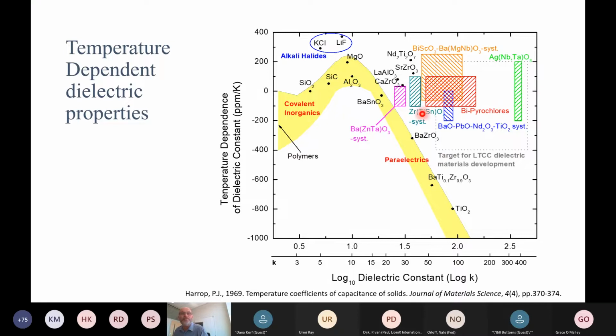Some of the more common ones that are used are the zirconium tin titanates, and some of the perovskites as well are very, very popular for filters and have been for quite a while. I'll show one example. We're looking at a ceramic co-fire where we actually mix pyrochlores to get a very nice permittivity range and also matching the temperature coefficient. So there's some work that we did to consider all the properties.